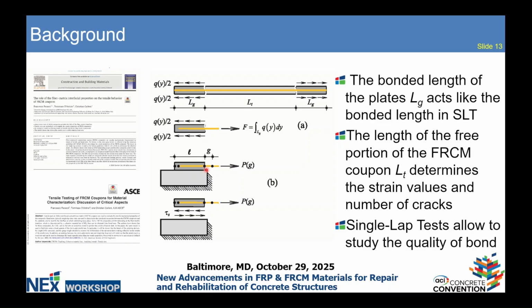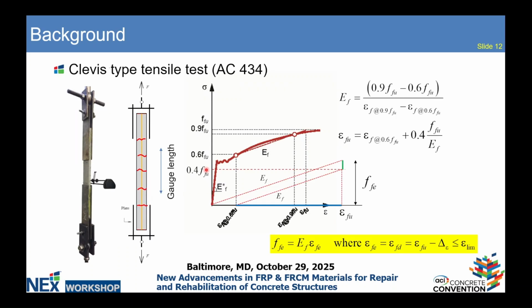Okay, and the other key point is that, again, this can be easily proven mathematically. The length of the free portion, L sub t, basically determines how many cracks you have, and because the strain is measured over the free part, it will give you different values of the strain. So in other words, if we test the same composite with different length of the plate and different length of the free part, let's say 3 different configuration, we will get 3 different of these responses, 3 different values of the strains, 3 different values of the elastic modulus. So this means that this test, as it is, unless we prescribe something more, will not basically give us a unique value for design. And so this is not probably ideal.